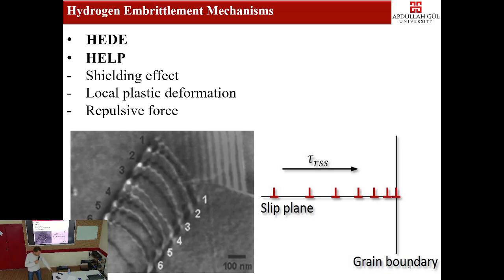We know that dislocations have a stress field, a tensile stress field and a compressive stress field, and interstitial hydrogen also has a stress field. According to this mechanism, hydrogen can shield the stress field of a dislocation, increase the mobility of the dislocation, and create some localized plastic deformation. And once that localization cannot be accommodated plastically, we have failure.